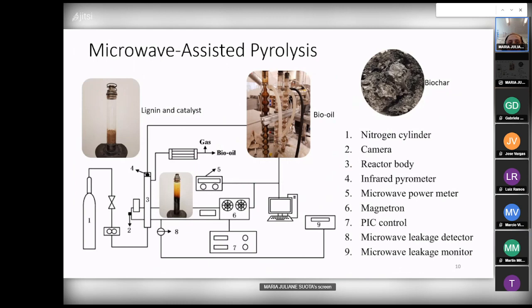The system I was using at UBC, University of British Columbia, was a microwave-assisted reactor. This system is famous for, or has several advantages concerning, the time of the pyrolysis, because conventional pyrolysis usually takes time and spends energy. And in this case, we could perform some pyrolysis experiments in shorter times, for example, 20 or 25 minutes, producing liquids, as we can see here, solids, as we can see here, and the gas.